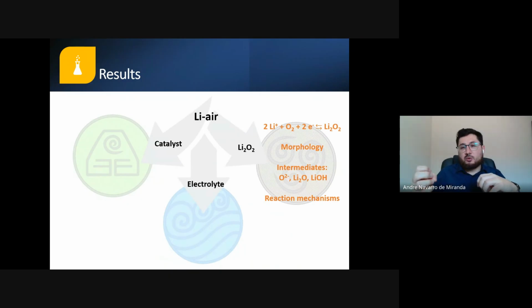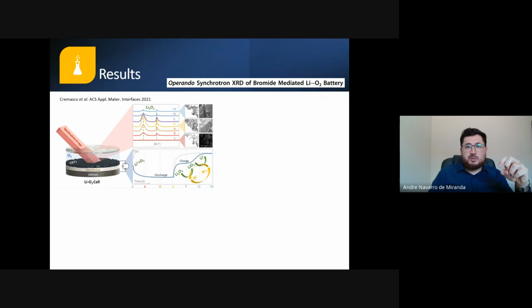So to form lithium peroxide, we can have superoxide particles. We can have lithium hydroxide in the process. Then we can understand better the reaction mechanisms. So this is one paper published in 2021 that studies the operando synchrotron XRD, X-ray diffraction, of bromide-mediated lithium-oxygen batteries. So the idea is we study the lithium-oxygen battery using bromide as a redox mediator.